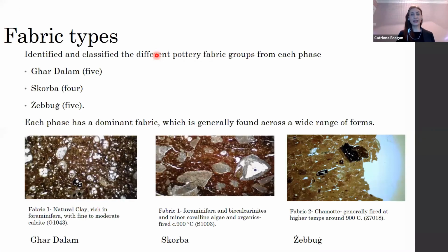So is there anything that we can actually say about these? Well, what we have now is a more nuanced picture of the fabrics used by the early Maltese potters. And what we can see is a number of different pottery fabrics were used during each of the 3 different phases under examination. So we've got 5 different fabrics for Ghar Dalam, 4 for Skorba and 5 for Żebbuġ. It was also interesting to note that each phase appears to have had a dominant fabric that is used across a wide range of styles and forms.